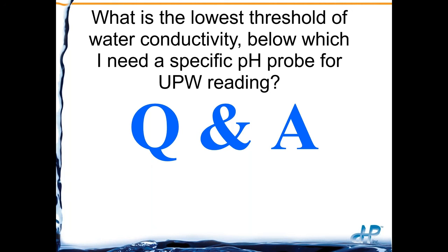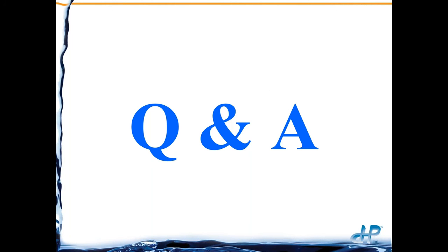But rule of thumb, 50 microsiemens, anything below that, if you don't have a pressure or flowing reference, you're going to get errors in your reading. Or not only errors, but you'll get very short life because the process will suck all the KCl out of that junction and shorten it, and you can't refill it.